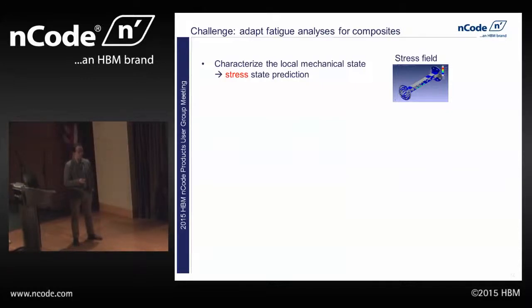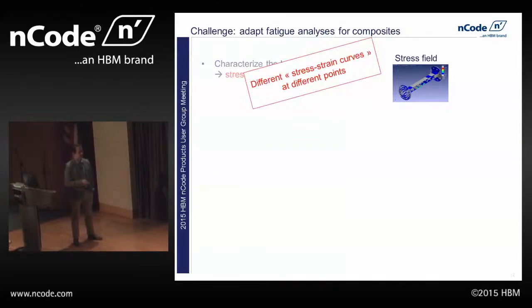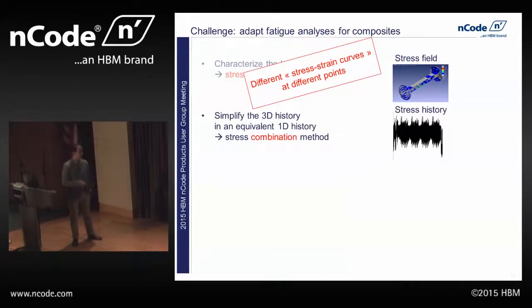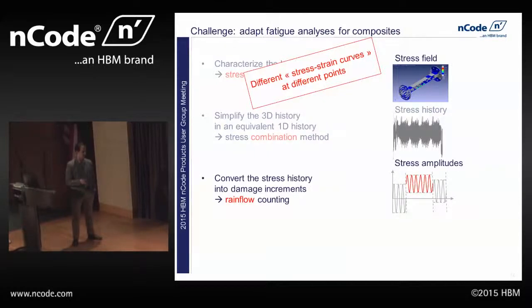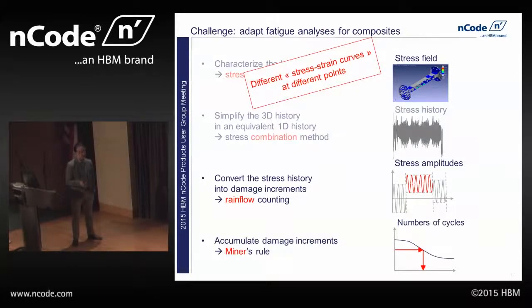So in the first step, we need to determine what our stress field is, because that stress field is what's really going to drive the durability or the fatigue life of our part. So if we look at predicting the stress field of these materials, one differentiation we see right away is that we know we're going to have different stress strain curves at different points. So we're not going to have this uniform stiffness happening across our part, and we're going to need to take that into account. From there, we can then simplify our 3D history into an equivalent 1D history using a stress combination method. We can then do our rain flow counting. And all that's going to happen very similar to the methodology you guys are used to.